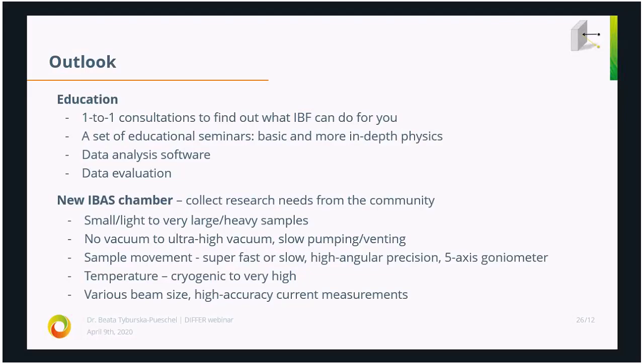Yeah, so generally we are planning to measure continuously, but we can, of course, also collect data in fluence increments. So we are aiming for a flux of 5x10^23 deuterium per square meter per second in UHV. So one can easily calculate how many seconds you need to reach a certain fluence, and generally that means that our measurement rate is faster than the flux. So we can easily measure this.